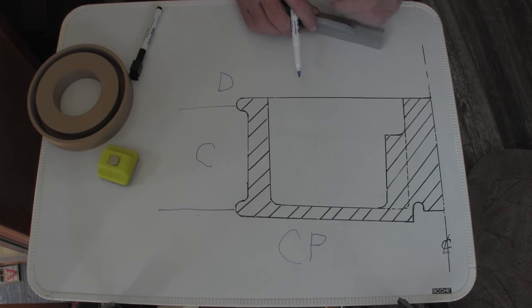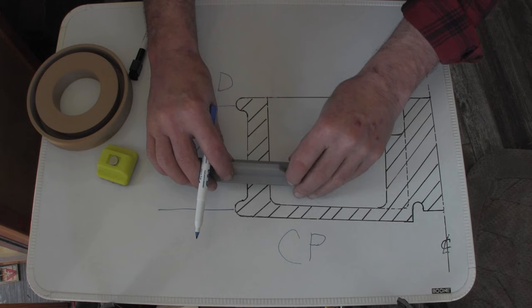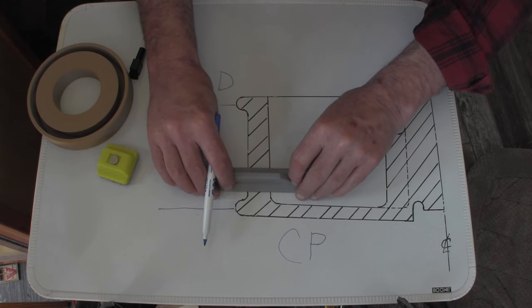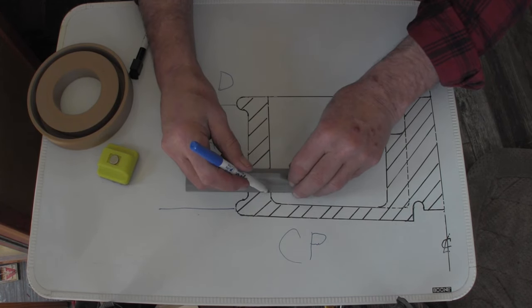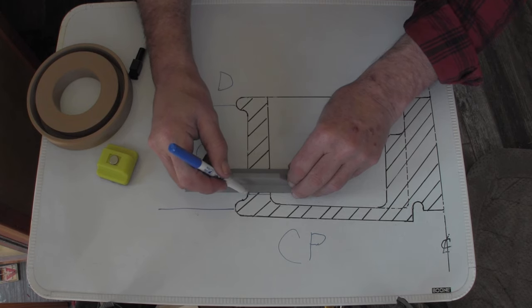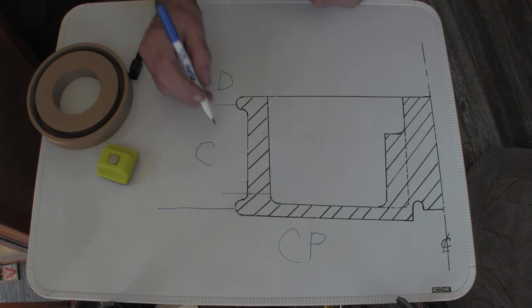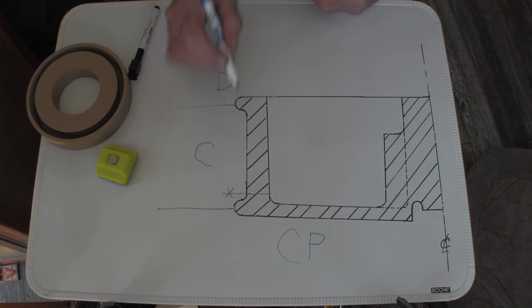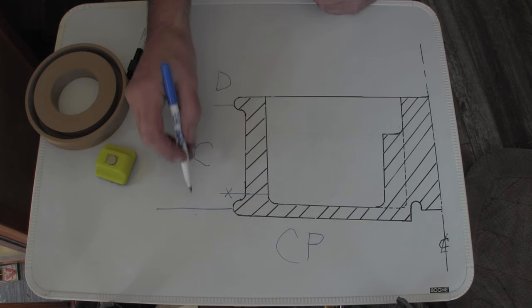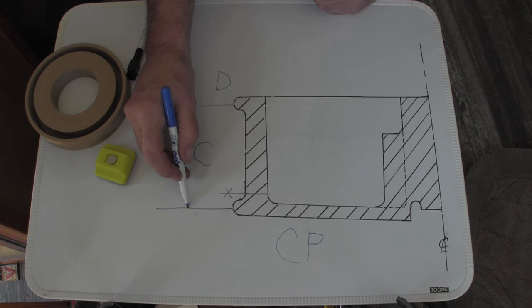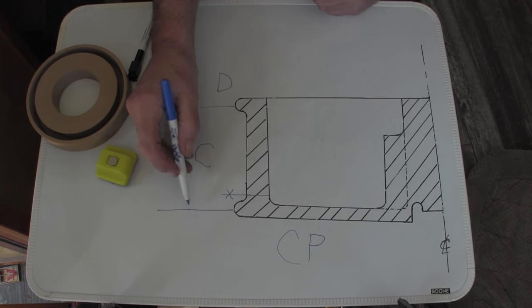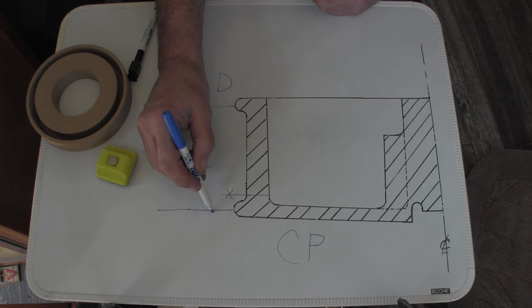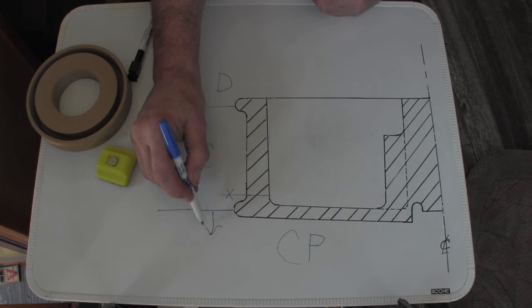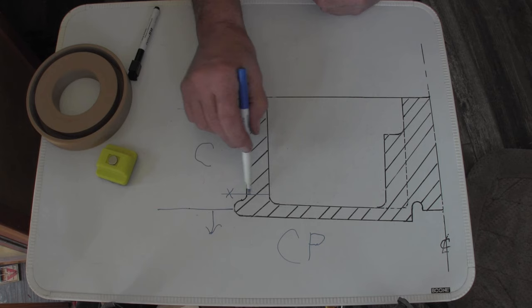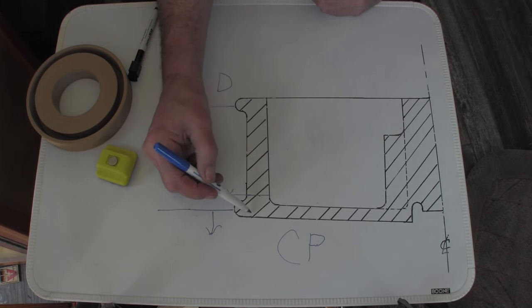So what you can do is you build a parting here just at the base of the fillet. So this is where the pattern is split at this point. And this is where the parting line is for the cheek to cope. So everything from here will draw that way. This part of the pattern from here, here to here, will also draw that way.